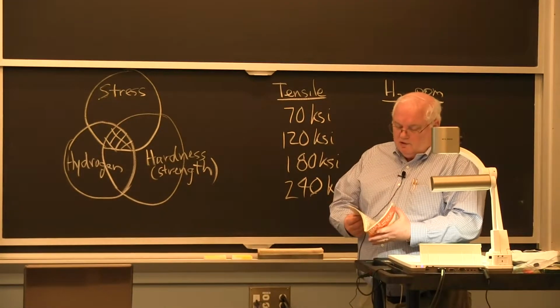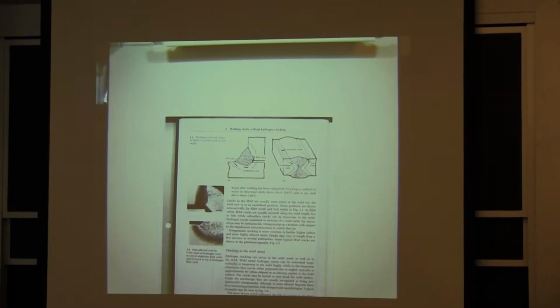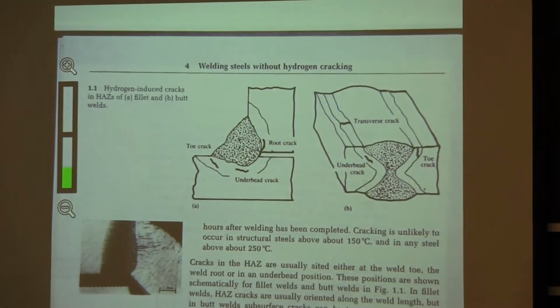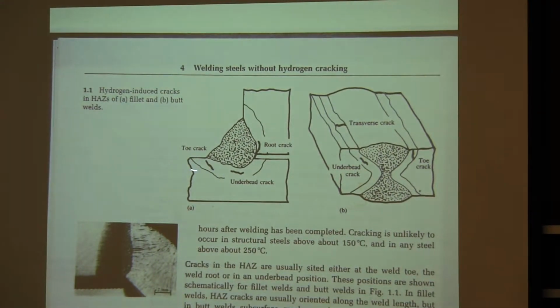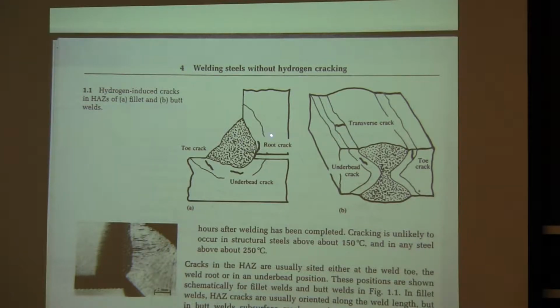So we've talked about faults in fusion welds and how hydrogen can cause cracking, and you get what are called underbead cracks, toe cracks. These are underbead cracks over here. This is a toe crack. Usually the toe crack's right at the toe of the weld. Root cracks come up from the bottom. Wherever you have a change in section, you have a stress concentration. Remember, the higher the stress, the higher the hardness, the higher the hydrogen level, the greater the propensity. And we use Venn diagrams to show this.